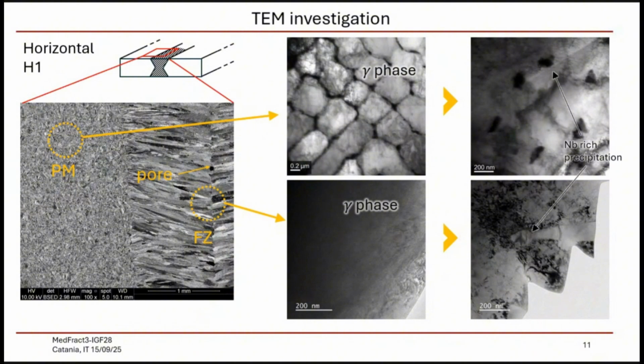By indexing diffraction patterns, we realized that only gamma phase is present, so we don't have any great precipitation of secondary phases, except for some particles, but they were quite rare. So these dark globules in the parent material and these lighter grains in the fusion zone are rich in niobium, but too small to get a precise indexing of the diffraction patterns, so we couldn't identify them yet.